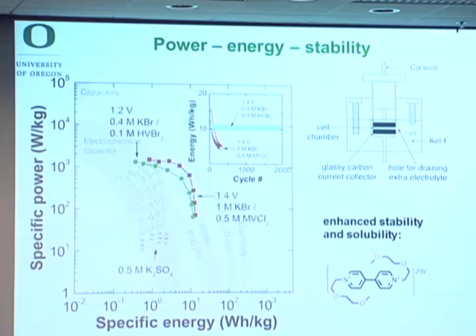So we can compare this now on this Ragone plot that I showed you right at the beginning. This is the same data with our data overlapped, and we actually designed a second type of cell to do this. One of the challenges in the capacitor literature is that nobody ever accounts for the volume and weight of their electrolyte in their measurements. They always just measure the carbon mass. But it's really important here because it's an active component. So we had to make a cell that you could really quantitatively get at the electrolyte mass.